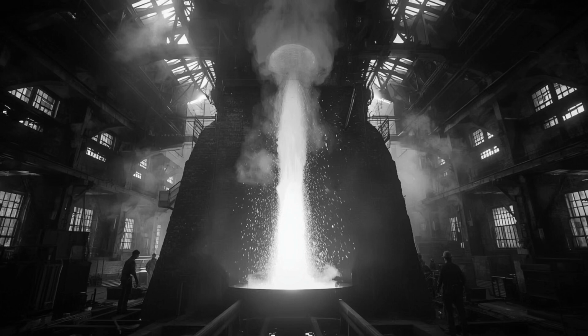By the third week, the thermal imbalance is no longer subtle. It's written into the very structure of the operation. The left side tap hole, always cooler, begins requiring longer tap times. The iron flows sluggishly, forcing the workers to keep the channel open for extended periods while the hearth drains. The slag, thick and viscous, clings to the runners and solidifies faster than the crew can manage it. They start bringing extra sand to bed the channels deeper to insulate against premature freezing.